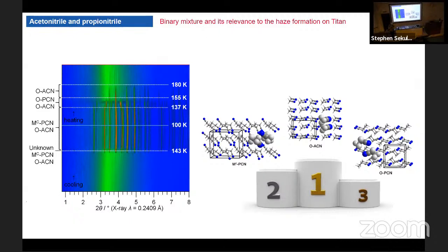Long story short, this is extremely complicated, and at first it does not make sense. But if you think about it, for all of these phases that exist, the energy minima are very related. So it's very easy to go from one structure to another. It's very easy to have quenching or not to have quenching. If you have a mixture with the sole existence of one phase as a crystal, it can nucleate another phase on top of it, and by that you can have a completely different sequence of polymorphs.